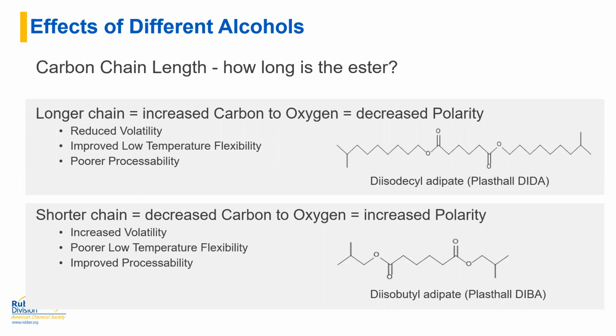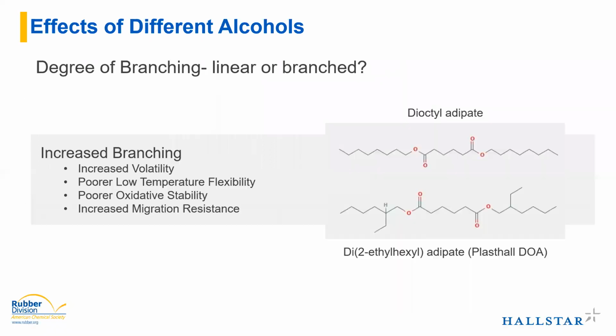You'll get reduced volatility, being a larger molecule, better low temperature flexibility, but you'll often see poorer processability because it's such a large molecule compared to their smaller counterparts. With a shorter chain, like diisobutyl, which has a very short carbon chain coming off of the ester groups, you'll see an increased volatility since it's much smaller, worse low temperature than with the larger material, but you'll see an improved processability. The smaller molecule is able to move more freely.